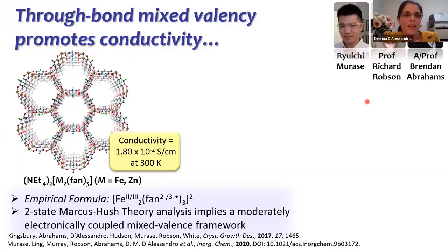This is a really beautiful example of a honeycomb framework, first published by Brendan Abrahams and Richard Robson at Melbourne University. In this material, which is in fact semiconducting in its as-synthesized state, the semiconductivity is attributed to the mixed valency not only of the iron, but also of the fluoranilate ligand. So it's a mixed valence framework with semiconductivity.